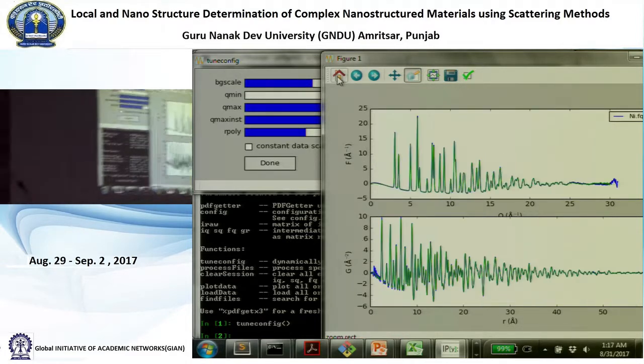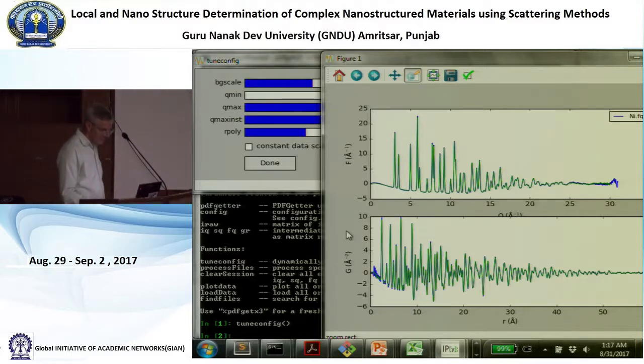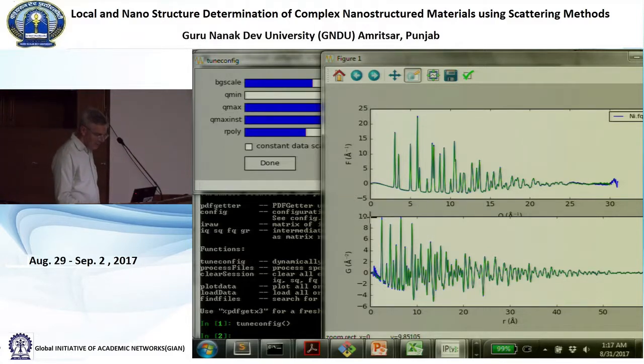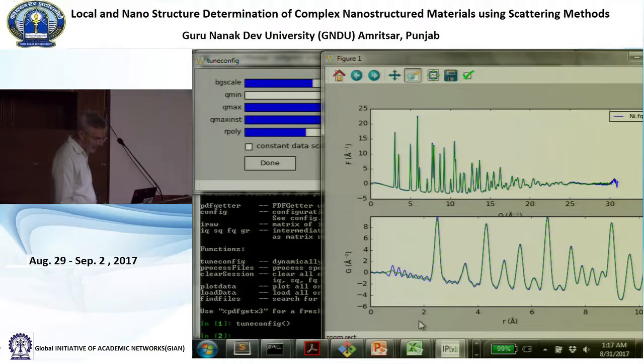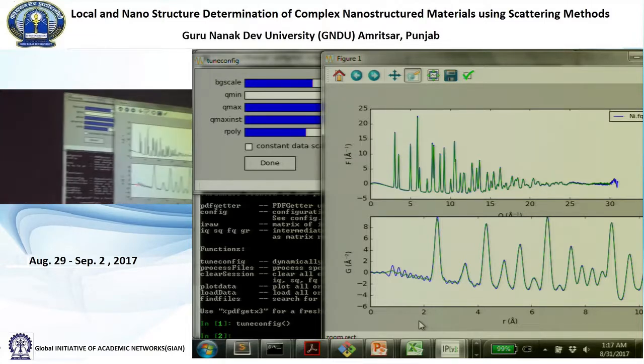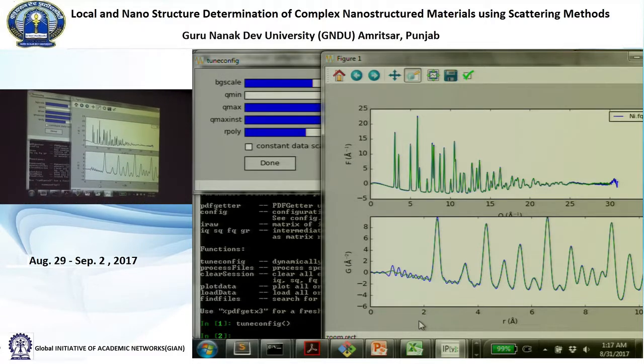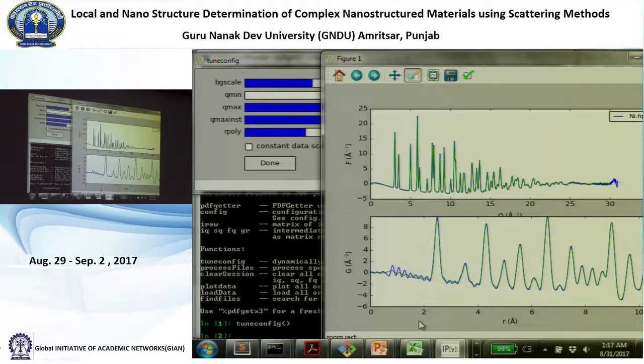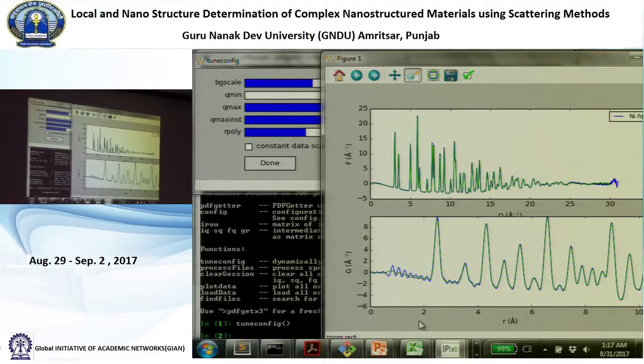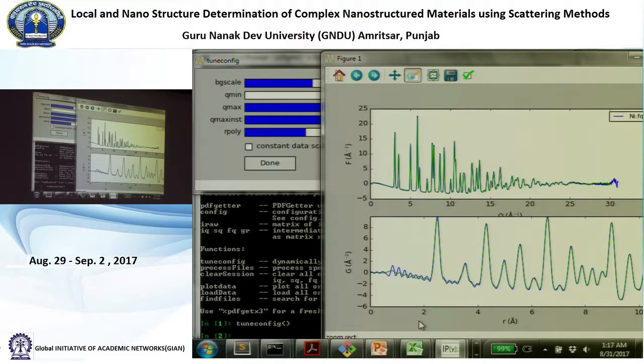Some of the biggest changes are maybe down here at low R. One thing that's happened is that we've decreased the size of the ripples down here, and that's because we've removed noise. So there's always this trade-off. If you go higher in Q, you have a higher resolution, but you have more noise. And so it was a good trade-off to not put this noisy stuff into the data.